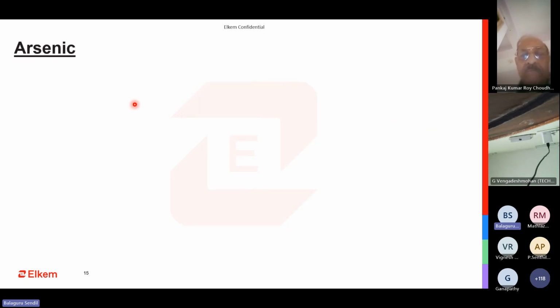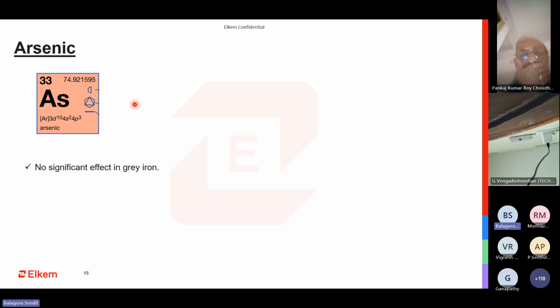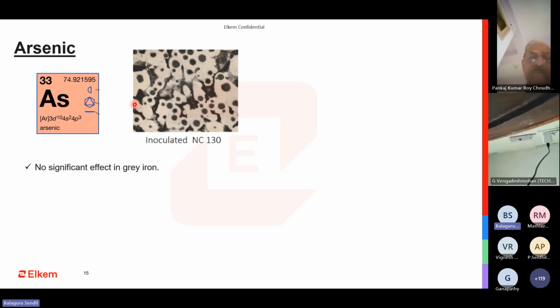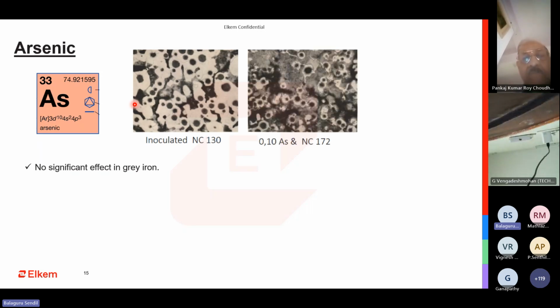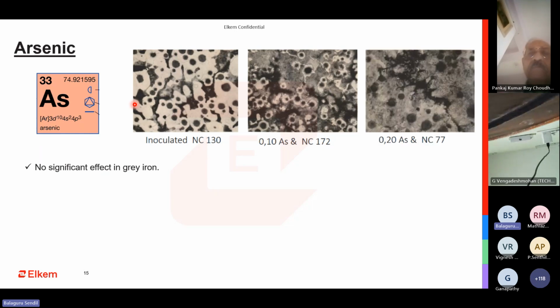Then the next one is arsenic. Arsenic has no significant impact as such in gray iron. This is not a concern for gray iron foundries. Inoculated, this is my nodule count for this condition. The base is such. When I'm adding arsenic, I don't see that much. At 0.1% it does a bit of refinement. But if I keep increasing it further, I see a drop.